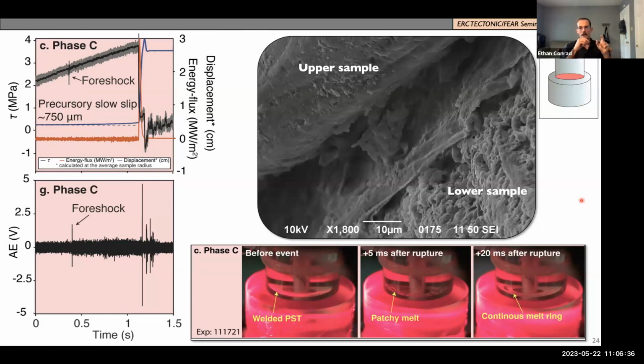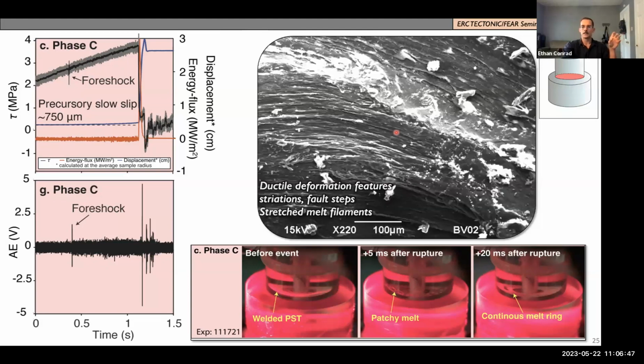In the SEM, we have some images of the interface between the two. This is taken at the edge of the sample, and we see these kind of globular melt forms connecting the two samples. And then I ignore these. I accidentally left them in here, but I'm just talking about stretched melt filaments here. Apologies for that, but these globular forms have been stretched out by the displacement and thinned and elongated, and that's what we're seeing, these elongate melt filaments on the melt patch.